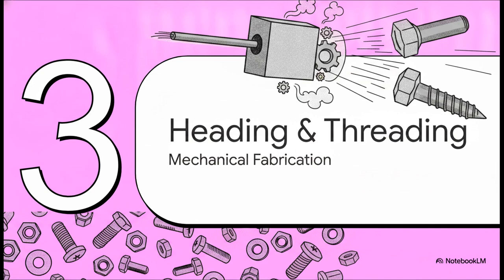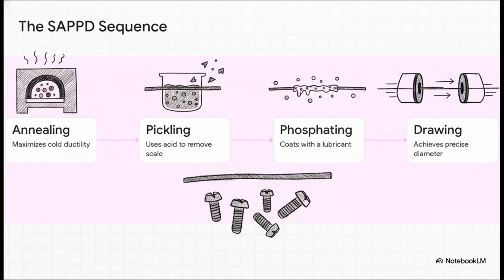Let's hit the factory floor. So we've got our carefully crafted steel rolled into long wire rods. But you can't just smash steel into the shape of a screw without prepping it first. It has to go through a sequence we call SAPPD. First up, spheroidized annealing. We use heat to turn the hard internal structures into soft spherical particles, making the metal as ductile as possible. Next is pickling, where we use acid to clean off any mill scale. Then, a zinc phosphate layer is added to hold lubricants. And finally, it's drawn through dies to get the absolute perfect diameter.